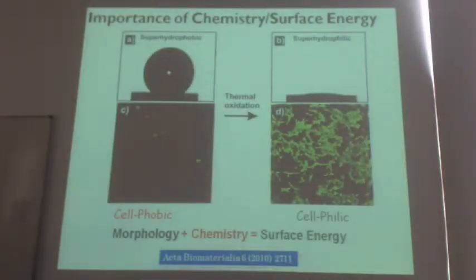But it is not only the topography, it is also the surface chemistry, what is said, the surface energy of the material. So we have shown this in this publication. We have started from a cell-phobic surface. Here is a cell-phobic surface. You can see it is superhydrophobic. So the surface can be switched to cell-philic upon the incorporation of a very thin nanometric coating. So the surface is switched from a superhydrophobic to a superhydrophilic state, and from a cell-phobic to a cell-philic state. So this points us to the importance of the synergy of the morphology and the chemistry, which is actually the surface chemistry.